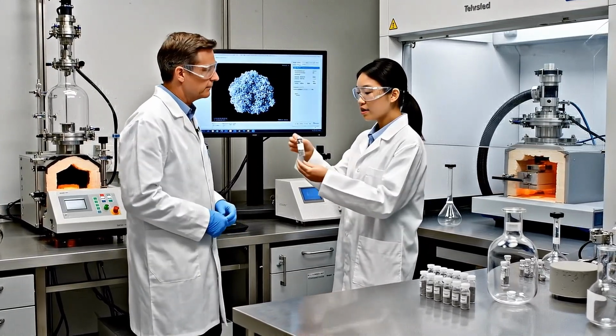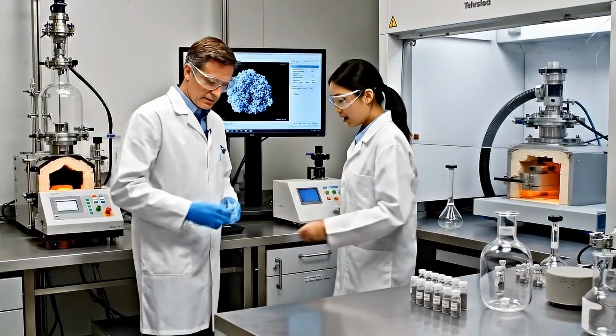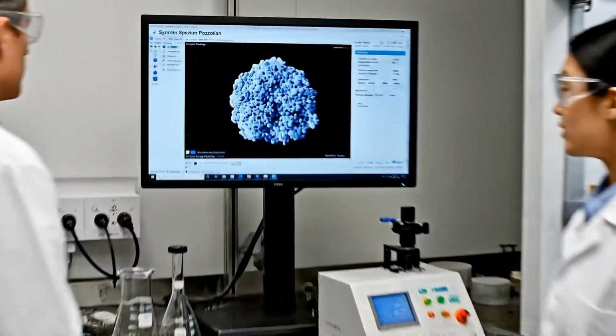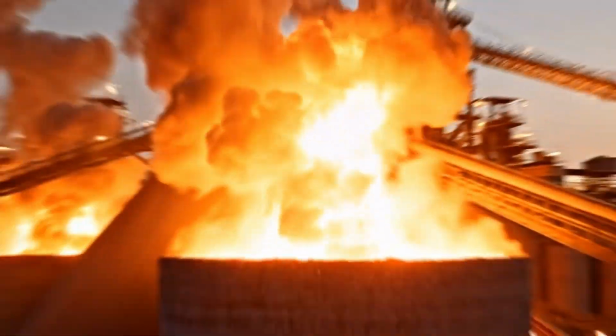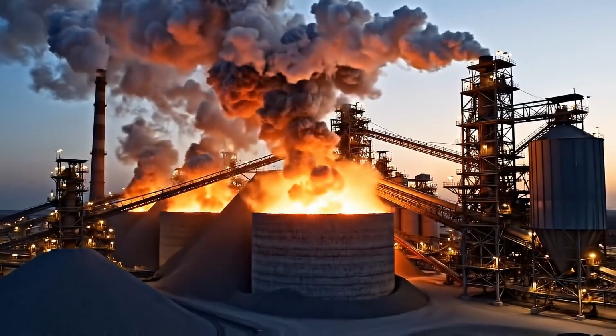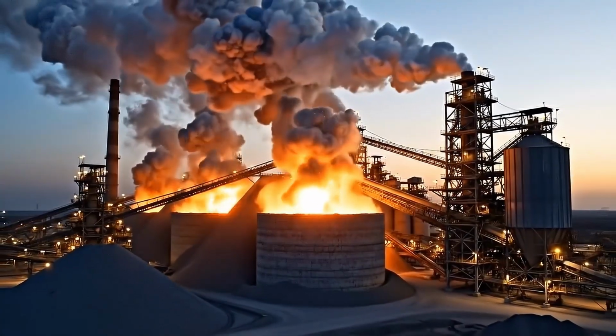This elevated-temperature batch production shows a mineralogically distinct, high calcium silicate matrix with a porous, branching microstructure. Within that matrix, incompletely reacted lime fragments were encapsulated not as flaws, but as chemical reserves, stored energy, reactive capacity, waiting for a trigger. The trigger is water.